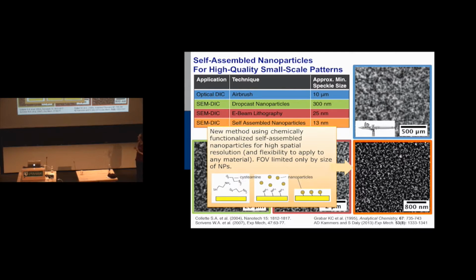And the reason that's fantastic for us is also because we can actually change the chemistry of the nanoparticle formation to get nanoparticles the size we want, so we can tune them to exactly the field of view that we want to investigate. There's a certain size of speckle or dot that you're tracking that will give you the highest resolution, and because we're doing statistical correlations on these deformations, we need really high resolution. If we can build our own nanoparticles and control them, then we can pick whatever field of view we want. And we can spread them over the entire surface, and then we can get multiple fields of view with multiple deformations in them and pull out statistically significant results. So it was very important to us that we were able to build our own as well and distribute them uniformly.